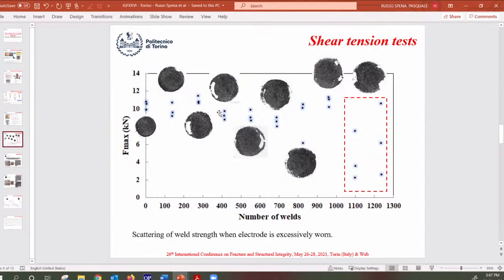You can see that over time, by increasing the number of welds, the electrode wear is particularly showing an enlargement of the cross-section diameter, and moreover a damage along the border of the electrode. You can see that after a certain time, the electrode was so worn that instead of having the traditional value obtained in the previous experimental test, we obtained a large scattering of the mechanical strength of spot welds. In some cases, we can find the highest strength value, but in other cases, you can see that the strength was very low.